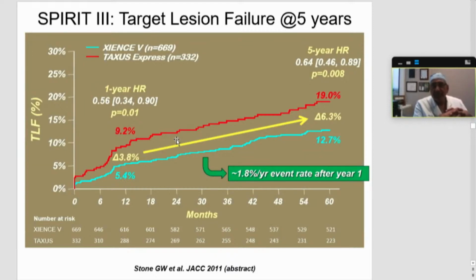Whether you take the XIENCE or the TAXUS, you basically can see that there are almost 2% event rates, 1.8% event rates per year after the first 2 or 3 years, and that leads to a TLF of 5 or 6%. It almost becomes 12 to 17% by the end of 5 years, and that's where we have to compete against other modalities of revascularization such as bypass surgery.